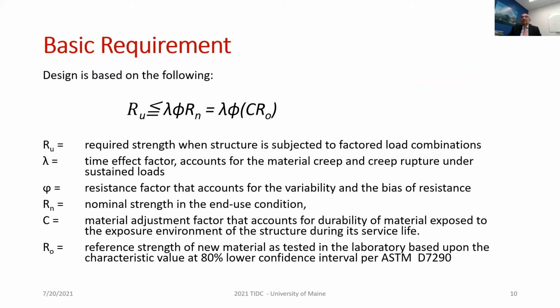Let's look at it in an equation. If R sub U is the required strength when the structure is subjected to factored load combinations, then this required strength should be less than or equal to the capacity. But how do we define the capacity? The capacity is the product of three terms. One is the time effect factor that accounts for creep and creep rupture, the resistance factor that accounts for variability of resistance and bias, and the nominal strength in the end-use condition.